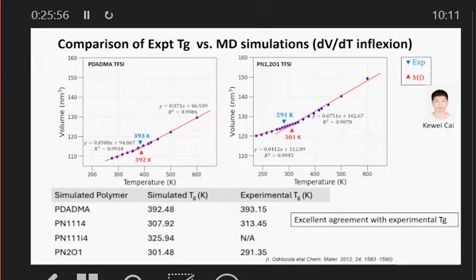But what we measure here is 392 from that inflection, 301 roughly to 290 here for this one, depending on where you take the intersection. And then when we correlate that to the published Tgs, we find in fact they're not bad. The simulated and the experimental are pretty close. So that would give us confidence that we can use this model now to start looking at what happens when we add salt to these systems. So very happy to see that was the case, and also interesting how much lower the Tg of the ether oxygen containing system is, and we'll look at that in a moment.